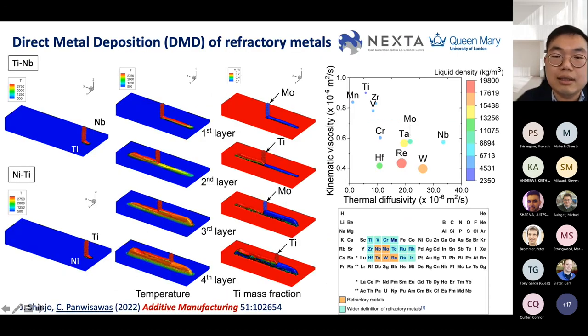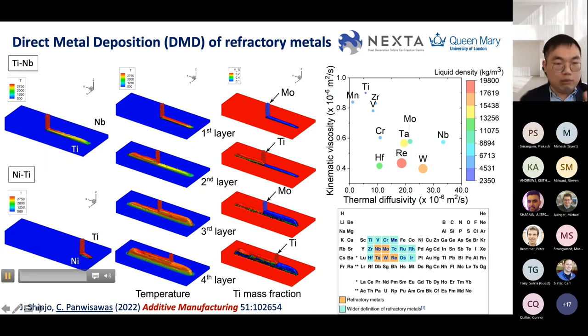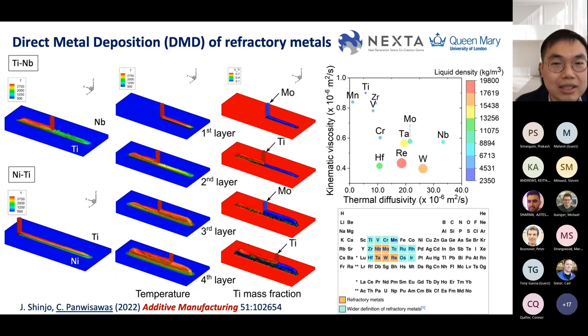And there is another process that I mentioned earlier, which is not part of it now. It is direct metal deposition, where you want to deposit different material on each other. For example, this one is kind of alternate titanium and a refractory metal deposition, where you have titanium niobium, for example, or titanium molybdenum here. And our study here is to understand how the species actually mix together, and what is the barrier when you want to actually use this direct energy deposition to repair some component.